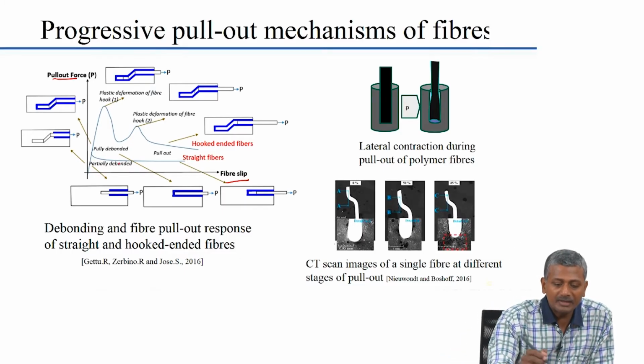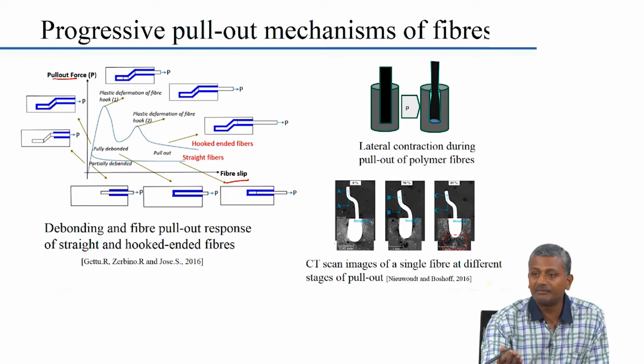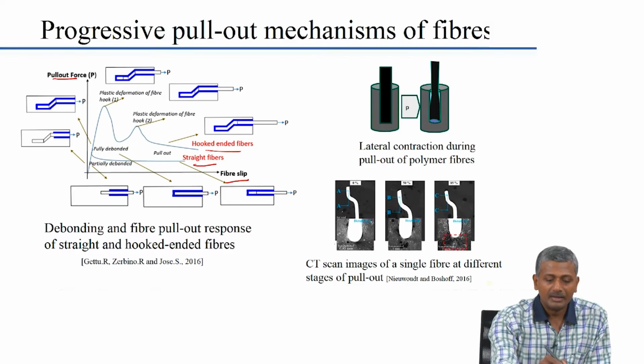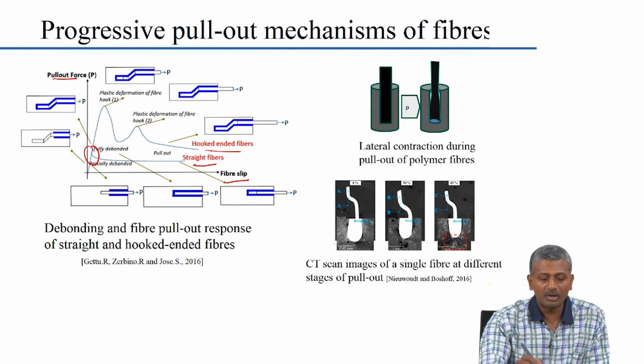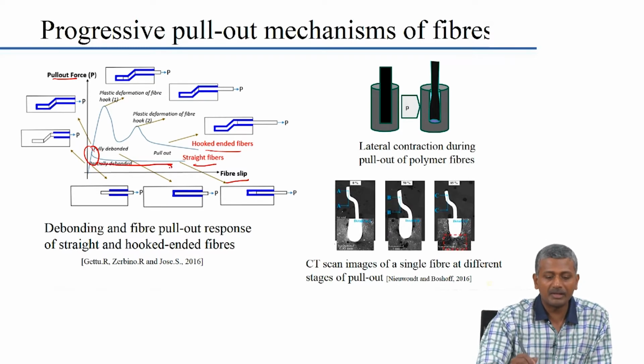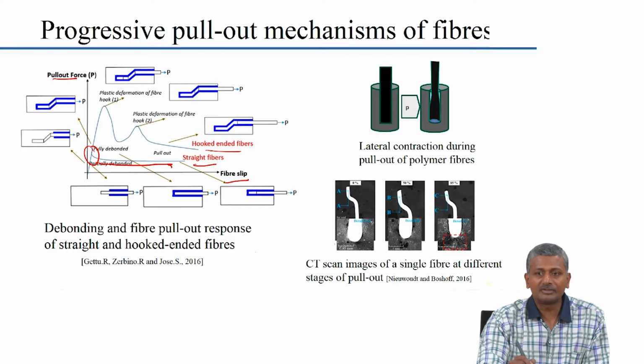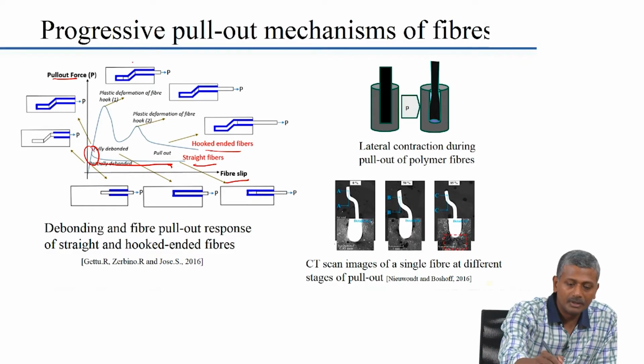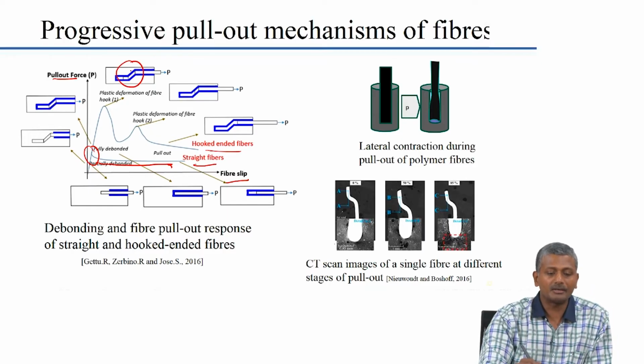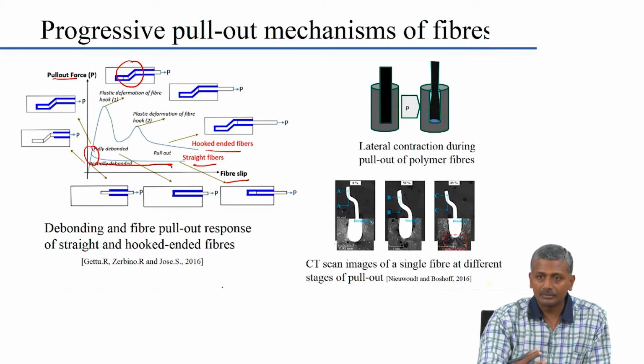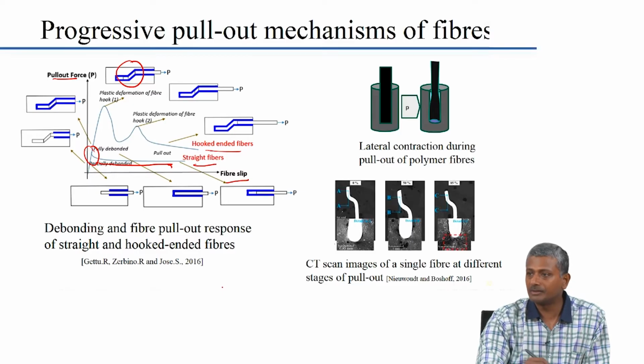So, you have different kinds of scenarios here, especially if you have either a plain fiber or a straight fiber or a hooked end fiber. What happens in the case of a straight fiber is that you get a complete debonding, and then the fiber simply gets pulled out of the system. In the case of a hooked end fiber, you have a slightly different sort of a system, because here in the initial parts you will actually get a transfer of stress across the length of the hook, and then the straightening of the hook will be happening towards the first part of the experiment.